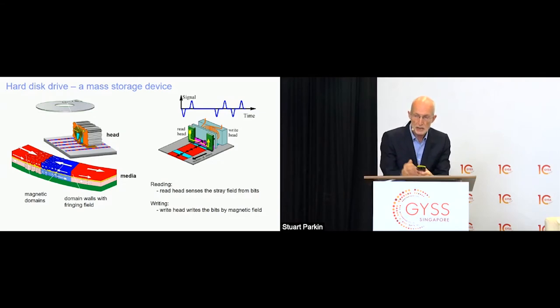one another. And in the presence of the stray magnetic fields, the fringing fields from magnetic bits in the magnetic layer, in the magnetic disk drive that's oriented antiparallel, these domain walls will have fringing fields which are detected by this recording head. And this device that I just described can detect these tiny fringing fields, which are 10,000 times smaller than any other device before this device.